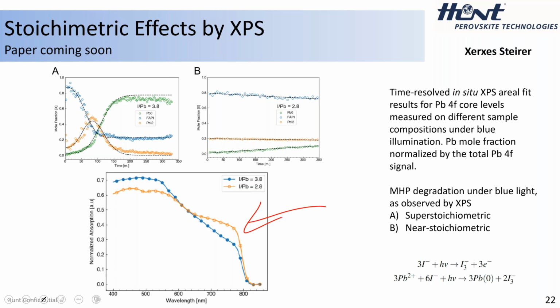Now, I'll bring your attention here to the bottom of the screen. You can see the two samples are actually remarkably different. The super stoichiometric composition here has a weak red edge versus the stronger red edge of the near stoichiometric material. Now you take that up here, to link this back to the previous conversation. Expose it to blue light under constant XPS measurement. And you can see that the formamidinium lead iodide in blue decomposes while the lead iodide grows and then eventually decreases, but then the lead zero grows in. So direct evidence from XPS that we're actually forming lead metal at the surface as the lead iodide decomposes. This is exactly what we saw in the XRD measurements, but we can see discretely where it's forming there on the surface via XPS.